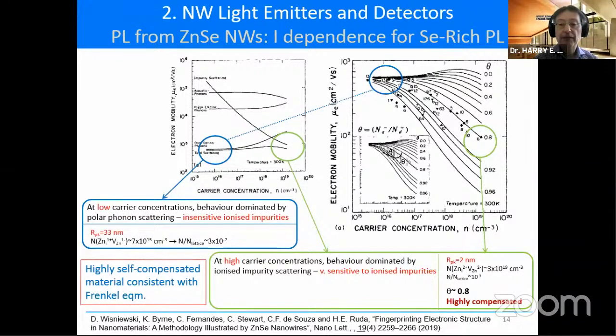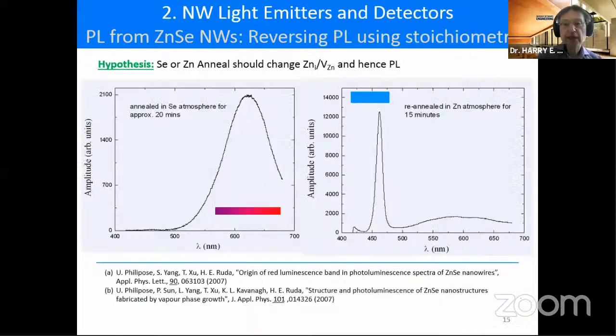And it's typical, believe it or not, of MBE grown thin films, which all follow along that same 0.8 line, roughly speaking, of compensation ratio. That is, the ratio between the ionized acceptors and donors is roughly 0.8, which means that these materials are highly self-compensated. And it shows up in transport, and it shows up in the optical response. That was the main point from this slide.